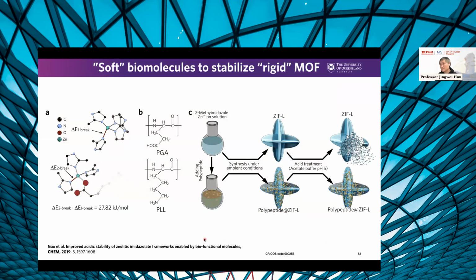The first thing is we do everything with a simulation and a calculation. Here we build a very fundamental tetrahedron structure for the ZIF, centered by the zinc and connected by 4 imidazolate linkers. So what happens if we intentionally break one imidazolate linker and connect it with a biomolecule, in this case, a polypeptide? We're creating defects, but to our surprise, this defect is not really a bad thing for the framework itself. It's actually making the remaining 3 bonds much tougher. The energy of breaking the bond actually increased by nearly 30 kilojoules per mole, which is a decent number. So this works in practice.